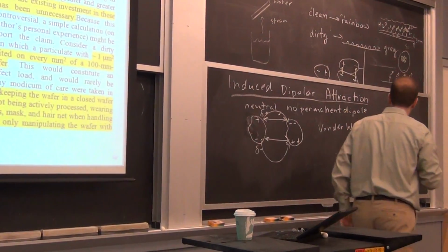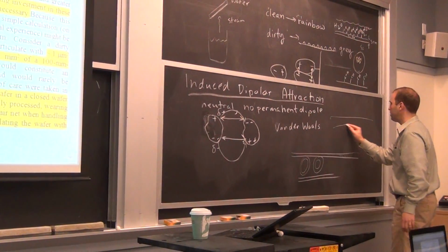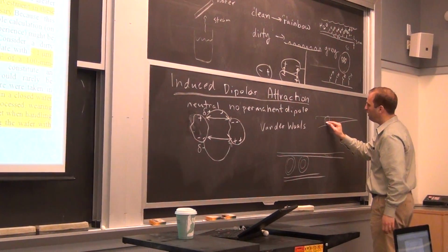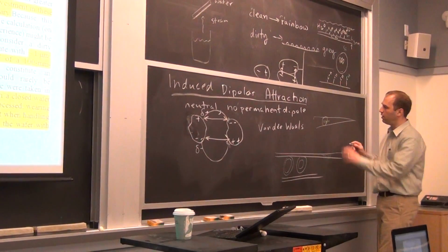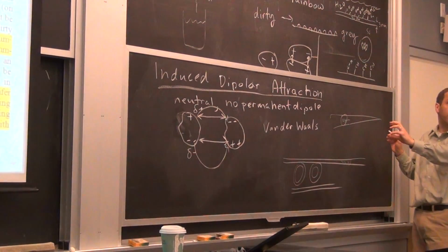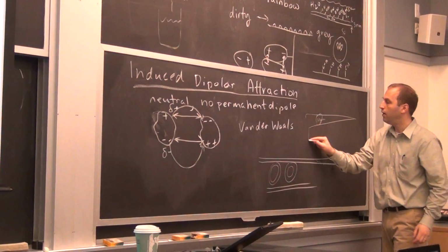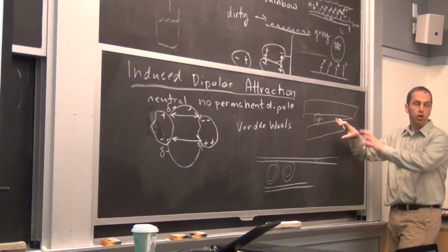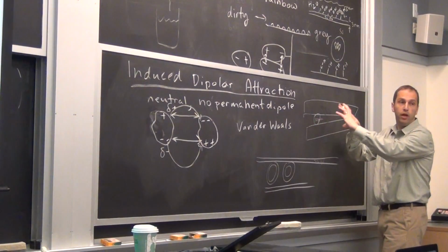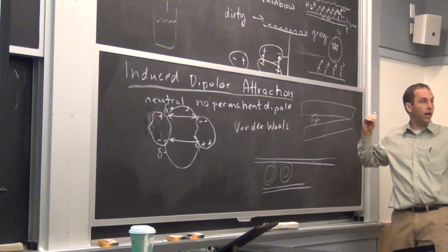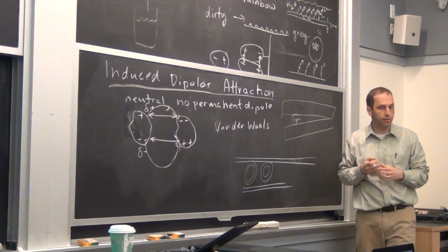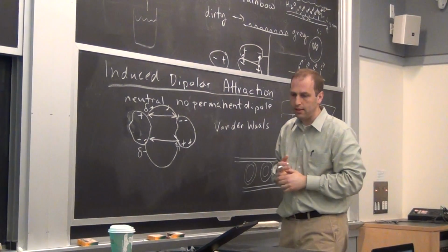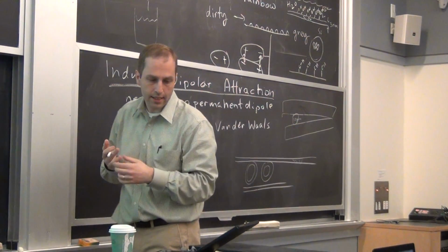Let's suppose that we have these two substrates. If you have even a 10 micron scale particulate in between them, it's going to cause a wedge if they're rigid. If they're not rigid, actually even this will not be a problem. You might get a local defect around it, but if they're compliant, they can still bond across them. So that's the other case where you really need a class 10 clean room.